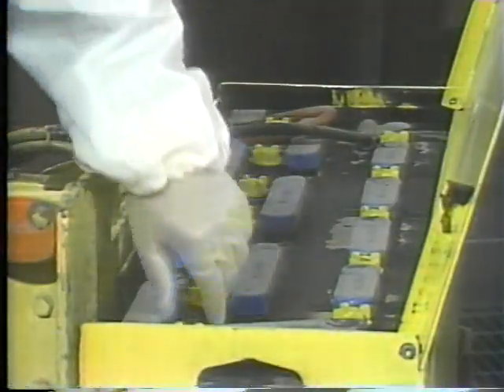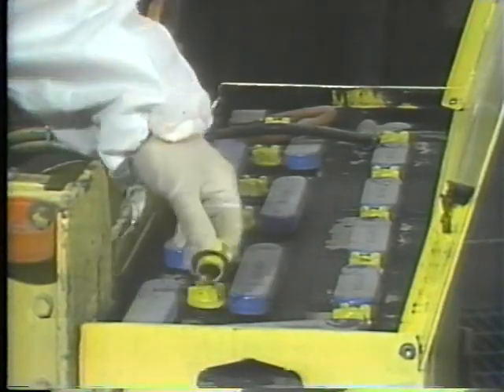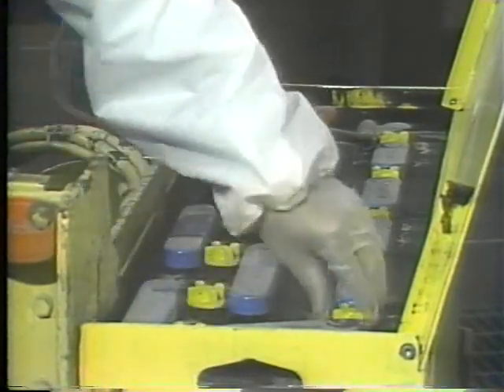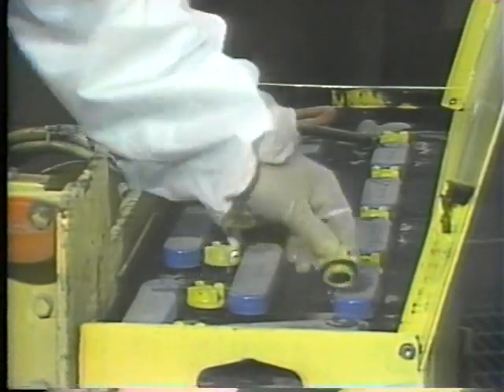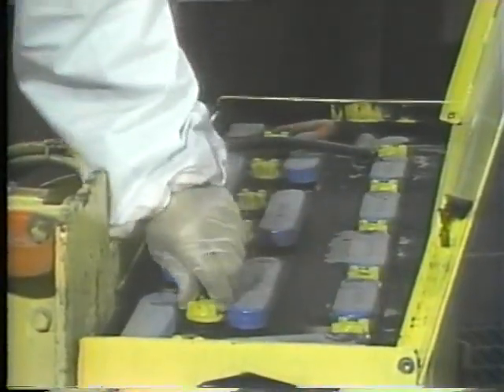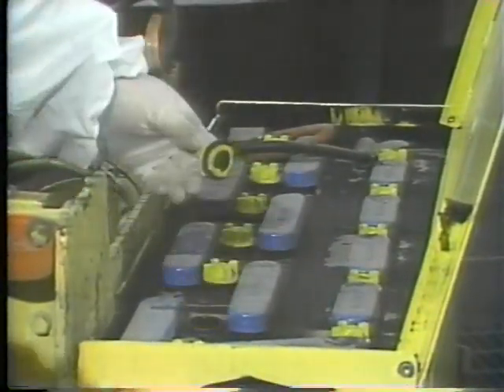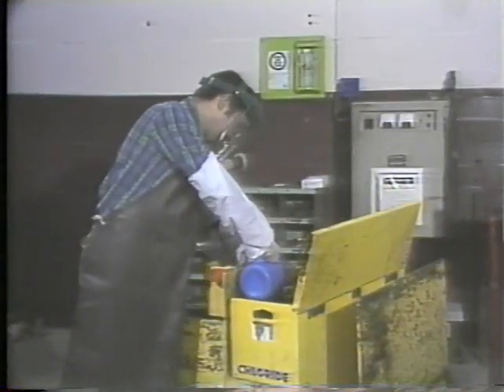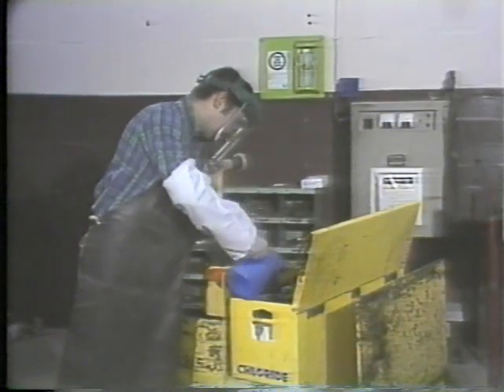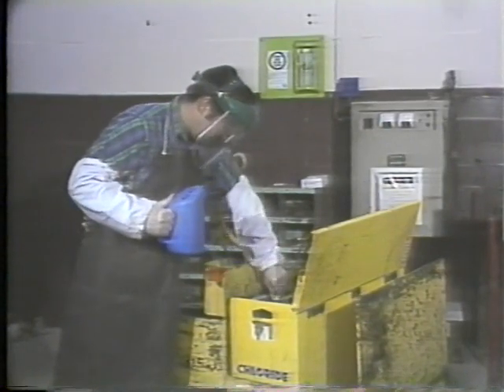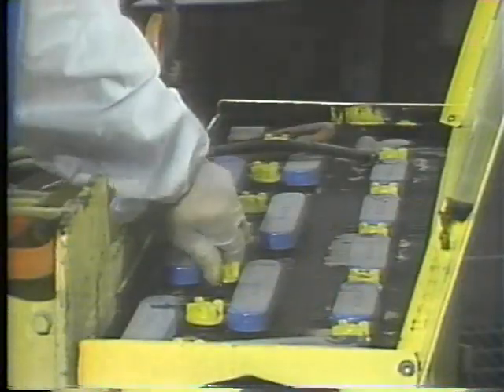The first step in the recharge procedure is to remove the vent caps and check the electrolyte level in each cell. There's a separate cap for each of the 12 cells in this 24-volt battery. If any of the cells are low, distilled water is added to bring the electrolyte up to the proper level. Distilled water is preferred because ordinary tap water often contains minerals that could contaminate the electrolyte and reduce the lifetime of the cells.